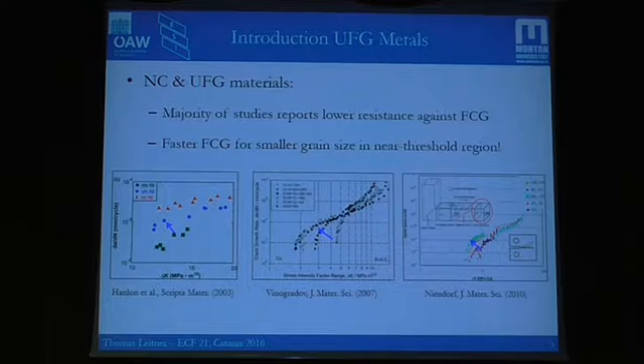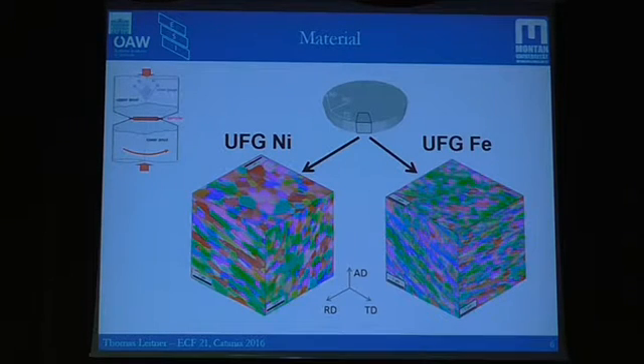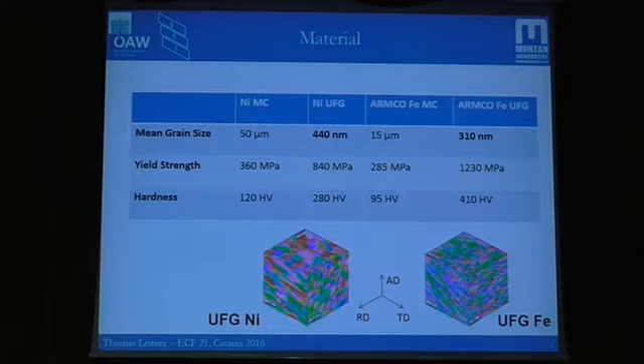So this could be a real drawback when we expect that components could get cracks during service, and also during production. That's why I would like to focus on the near threshold behavior of these ultrafine-grained metals and tell you a bit about the reasons and our findings. I did my studies on ultrafine-grained nickel and iron, produced by high-pressure torsion, as shown here. By severely plastically deforming these materials, we get severe grain refinement, with grain sizes of about 400 nanometers for nickel and about 300 nanometers for iron. This is accompanied by a significant increase in the yield strength, as can be seen here.